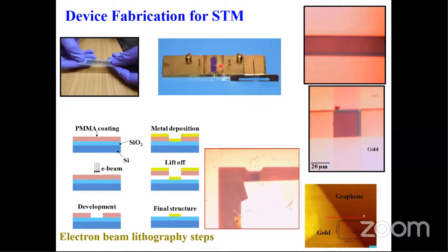So this is a technique which we call wire masking. If you place a wire, you see this is the graphene, if you can see on your side, and these are the gold contacts on both sides of this graphene, okay? One can also cover from four sides by doing another wire masking in this direction, so that you can see this kind of structure more clearly optically. And that is a good idea when you are doing STM, because one has to align the STM tip nicely with this region, which is around 20 by 20 microns. So it's quite small. This can be quite challenging.